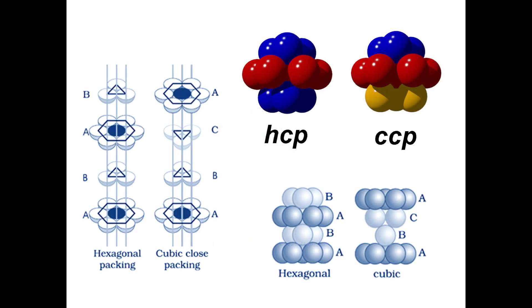Let's end this video by looking again at the difference between hexagonal close packing and cubic close packing, this time in a slightly different way. The ABAB packing of hexagonal close-packed structures gives layers of hexagons and triangles, repeating in columns. By comparison, the ABCABC packing of cubic close packing gives layers of hexagons, triangle, triangle, hexagon, with the two triangles oriented in different directions.